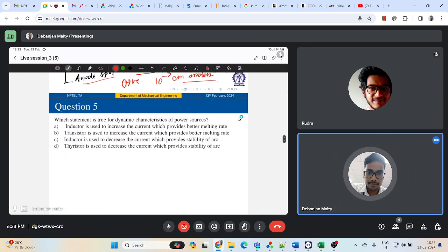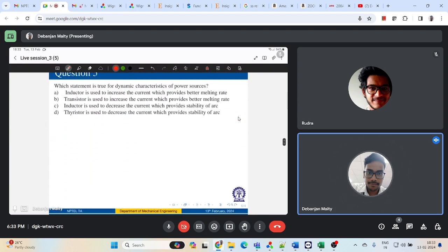Now it has been experimentally found, and we have talked about thermionic emission already, that if you have some known arc length, so for a given spacing, the voltage reduces up to a current value of some 50 amp, and then it increases thereafter.